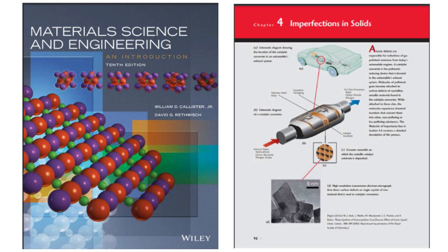As those pollutant molecules, like carbon monoxide or nitrogen oxides, hit those active sites on the catalyst surface, they get temporarily trapped. And this allows them to interact with other molecules, like oxygen, and rearrange themselves into less harmful substances, like carbon dioxide and nitrogen gas and water. So those tiny imperfections on the surface